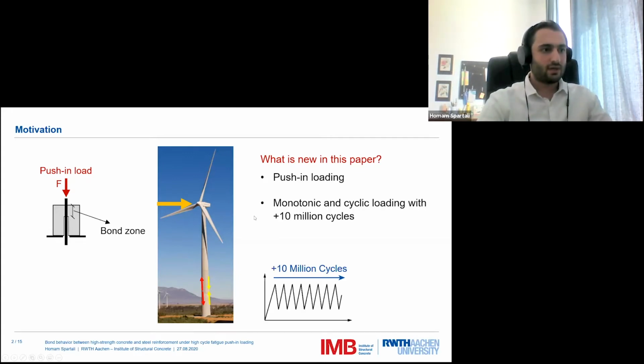These types of structures are also subject to high cycle loading, which may be more than 10 million load cycles through their lifetime. So in this research, we considered this also. And because of the increasing utilization of high strength concrete, we also used concrete mixtures up to a compressive strength of 120 megapascal.